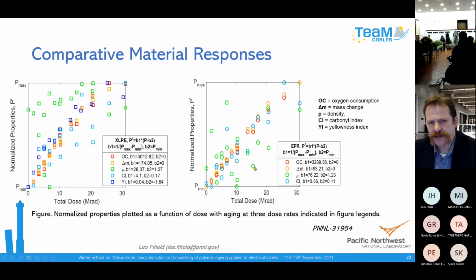Unfortunately, oxygen consumption and mass change are limited to laboratory techniques. It's difficult to measure that for insulation on an installed cable. But this effort showed that those are valuable tools for doing accelerated aging. The understanding is that if we try to do accelerated aging at mild conditions like 90 degrees C, 100 degrees C, where it's going to take many years to come to completion of aging, we can maybe get those early data points and extrapolate the aging from a mild condition in a reasonable amount of time. So that's it for that section.